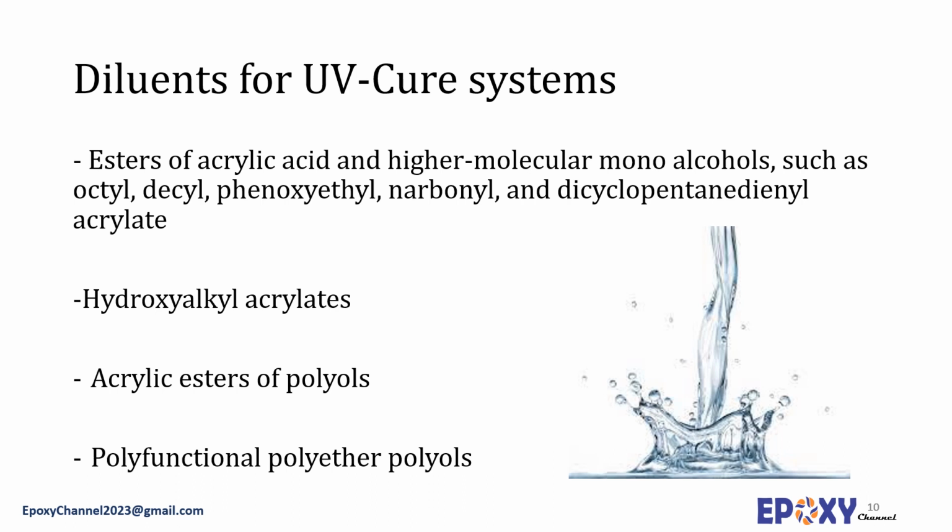Concerning the health hazards, the esters of polyfunctional polyether polyols are less risky. This group includes diethylene diacrylates, dipropylene diacrylates, and acrylic esters of ethoxylated polyols such as glycerol, trimethylol propane, ditrimethylol propane, pentaerythritol, and dipentaerythritol. Thanks to the mobility of the ether groups, polyether polyols confer optimum thinning properties, and the produced films are also flexible. However, the presence of the ether group impacts the weatherability.